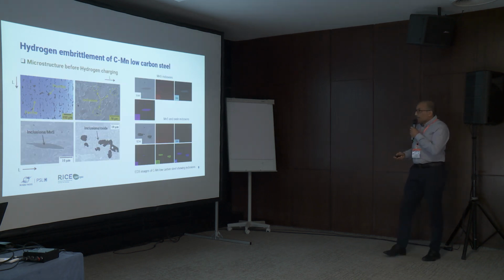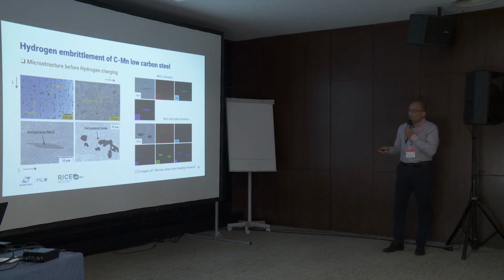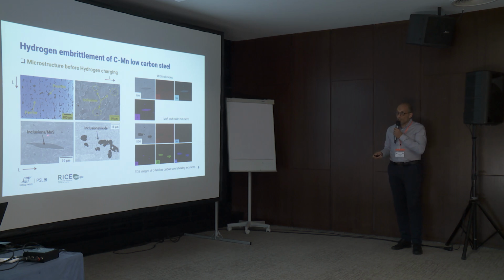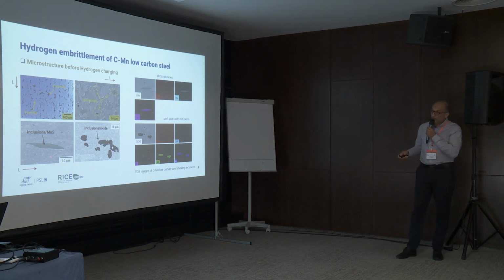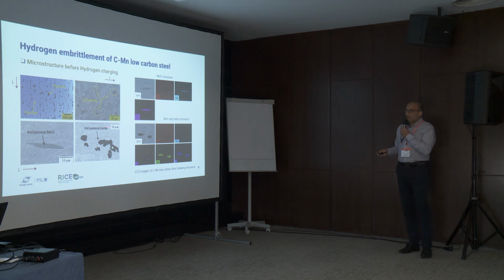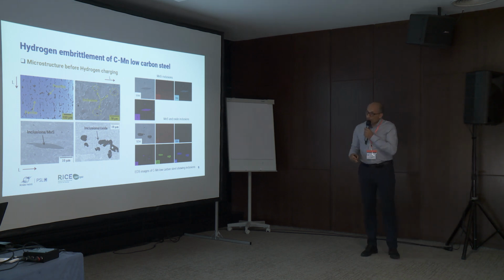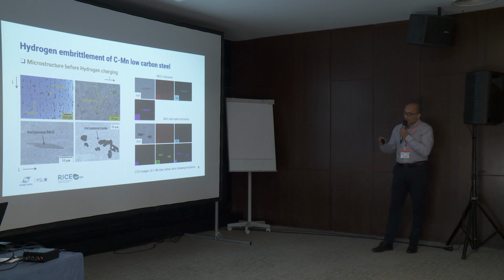Okay. Here is the microstructure before hydrogen charging, a classical ferrite-perlite microstructure. You can see some alignment of the perlite along the rolling direction, the L direction. There are some inclusions of two populations: MnS, manganese sulfide inclusions aligned along the rolling direction, and a mixed population of inclusions composed of alumina oxides mixed with MnS.